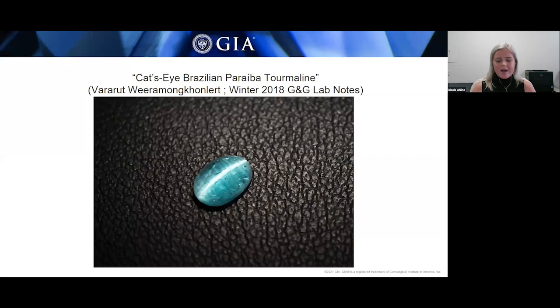The chatoyancy phenomenon seen here is created by layers of fine parallel growth tubes that were positioned just above the base of the cabochon. So with the vivid blue color and that well-developed chatoyancy seen in this Paraíba tourmaline, also originating from Brazil, this makes this stone a pretty rare find.